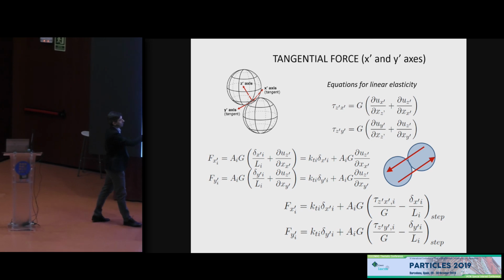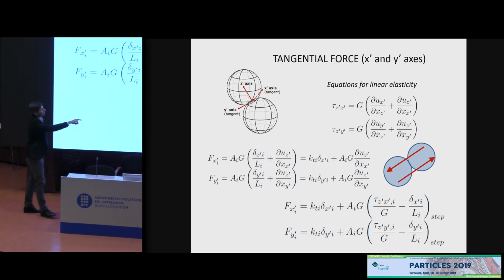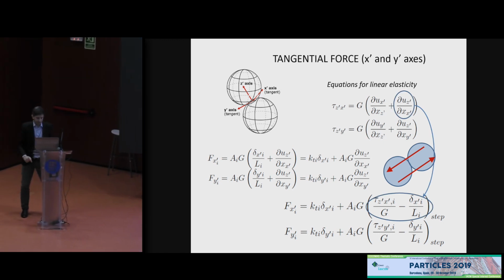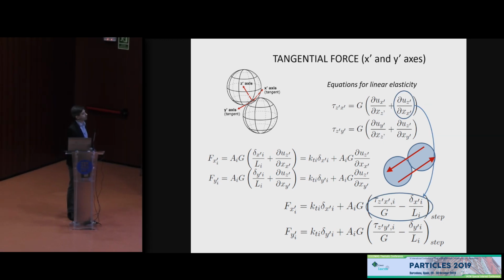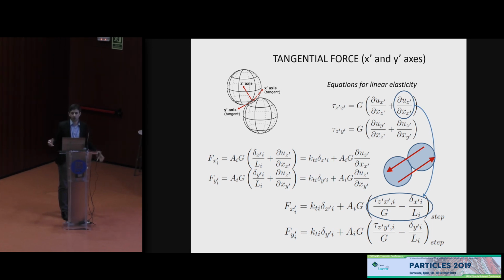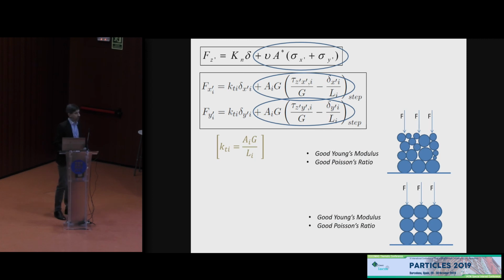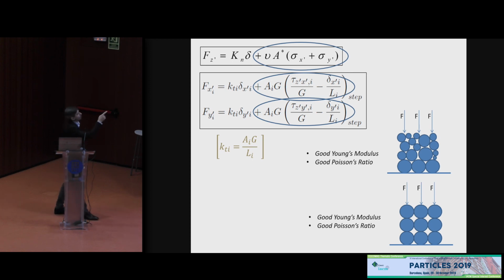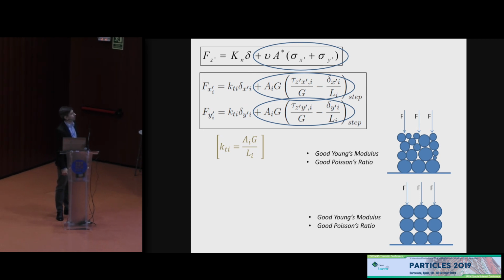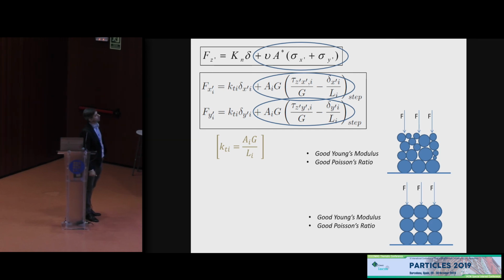It's the same idea. So there we substituted those derivatives. Here is marked. Those derivatives are substituted by an expression which uses the stress tensor, which has a lot of information from the surroundings. When we did this, we used the expression for the normal force with the extra term and the tangential forces with the extra terms as well. And also, here we realized that the Kt, so the tangential stiffness, is not changing, it's fixed with the value of AG divided by L. Then we achieved what we wanted. A good result for the Young's modulus, Poisson ratio, for any packing, basically.